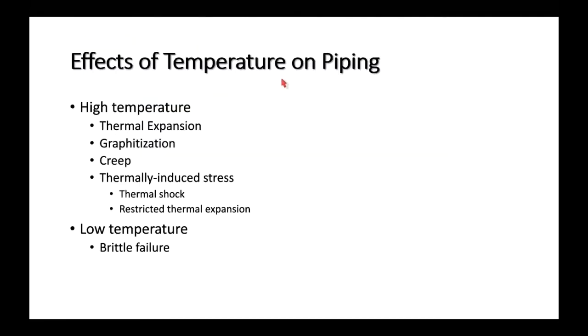Okay, let's just see how well we've done. Thermal expansion, yes. Creep, yes. Thermally induced stress. Restricted thermal expansion. Oh, look at this. Low temperature. Yeah, so that's an effect on piping. Brittleness at low temperature. And so if we have a pipe that's being used in cryogenic service or refrigeration service, we might want to have steel that's alloyed with nickel to improve its nil ductility transition temperature. Right, so we want to make it ductile at low temperature by adding nickel as one of the main alloying agents that increases toughness and ductility at low temperature and keeps it from getting brittle.